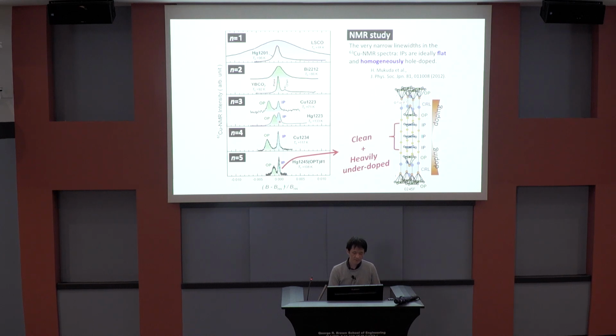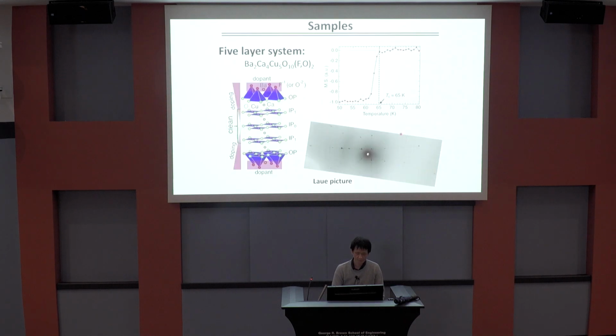YBCO and mercury cuprate show very sharp peaks, which can be expected from the observation of quantum oscillation, but the multi-layer system shows much sharper spectra in NMR, especially this peak, which becomes sharpest in the inner layer of a multi-layer system. So we can get a very rare case of clean plus heavily underdoped state in the inner layer of a multi-layer system. This is the sample we studied.